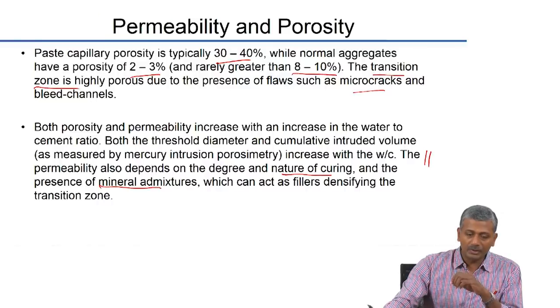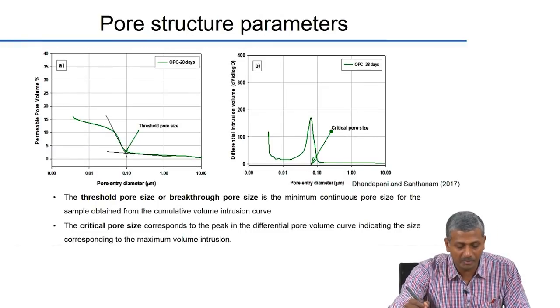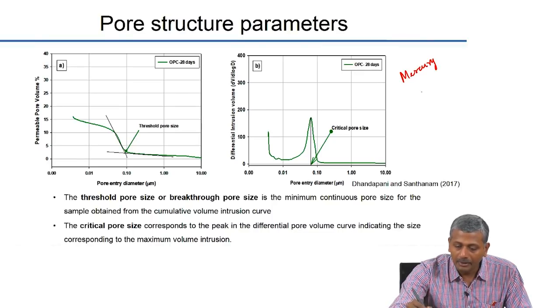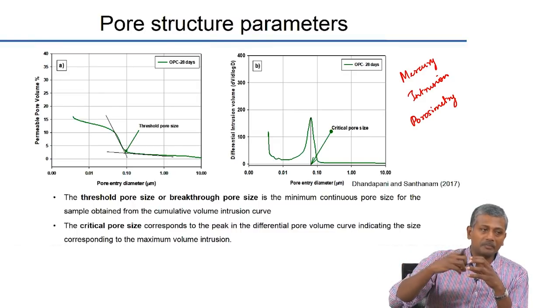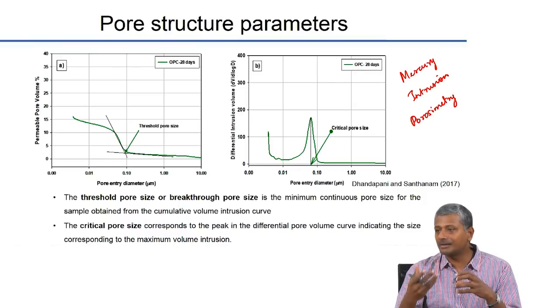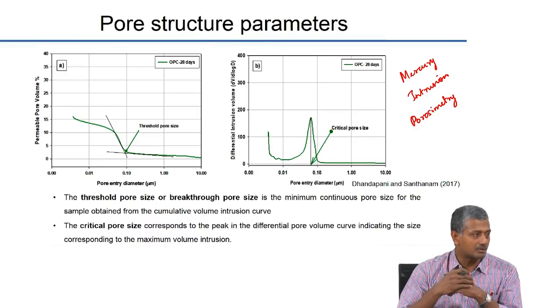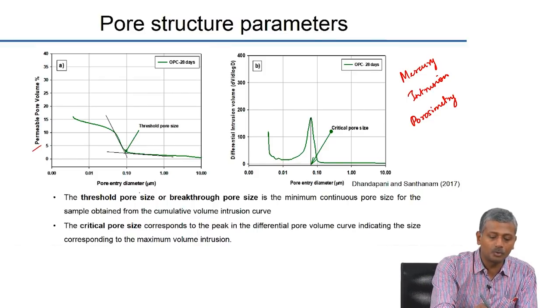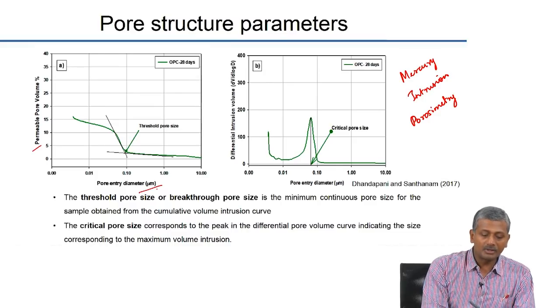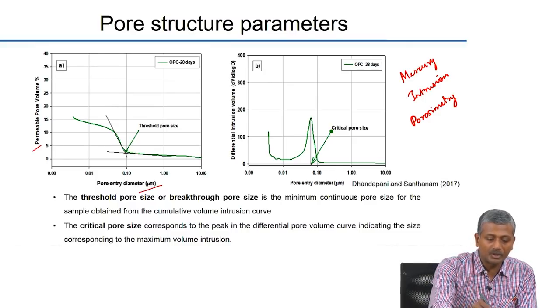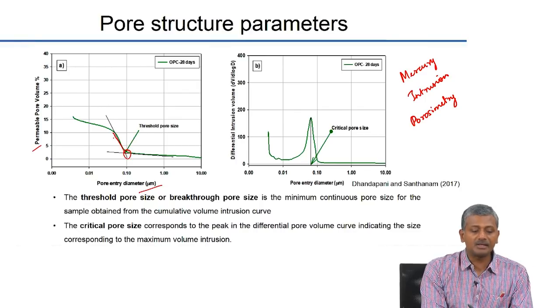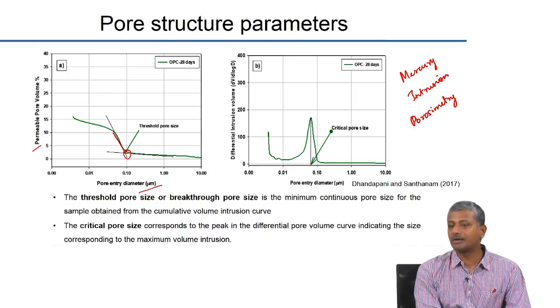the mineral admixtures. So, if you look at data from mercury intrusion porosimetry, this experiment is called MIP, or mercury intrusion porosimetry. So, here what is being done is you take mercury and you cause this mercury to percolate or penetrate the pore system of the concrete under increasing pressures. So, when you increase the pressure, the mercury is able to penetrate smaller and smaller diameters, because pressure is inversely related to the diameter. So, here the permeable pore volume is plotted against the pore entry diameter on the x axis. So, here you can see that the permeable pore volume is quite low until here, but all of a sudden there is an increase in the permeable porosity in the system at a particular pore diameter that is close to about 0.1 micron. We are talking about 100 nanometers, right?